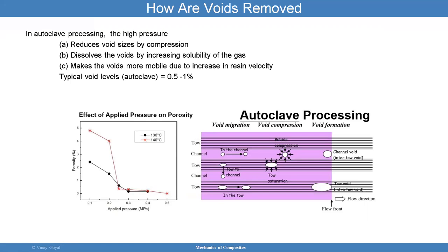Say you have a sandwich core, and we discussed sandwich core last week. You have foam, and then you have facesheets. If you apply too much pressure, you could crush the core. And I'll give an example later on about this. With autoclave processing, I want to show you what's going on. You have these voids that are going to try to escape, and we're hoping it could occur through bubble compression. So the void is migrating, the void compression, void formation, and finally, boom, it goes out. And that's what we want to see.